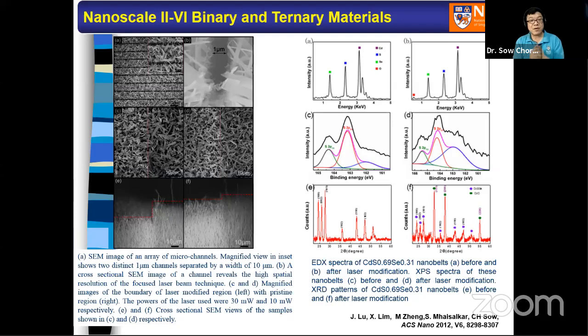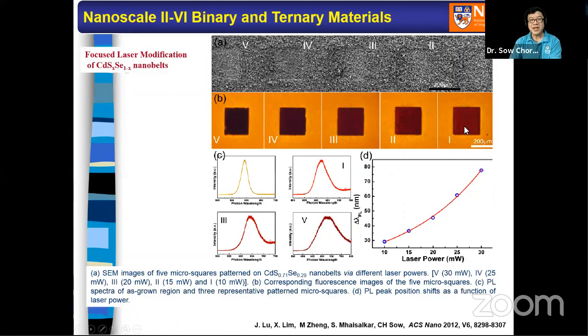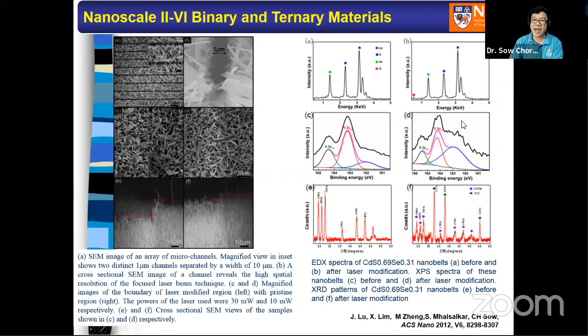And since the band gap of this material system is a sensitive function of the relative proportion of sulfur and selenium, when you use a laser beam to locally change the chemical composition ratio of sulfur selenium, you change the band gap. Hence, you change its color of fluorescence in this way. So this is a very nice way of a photochemical reaction.